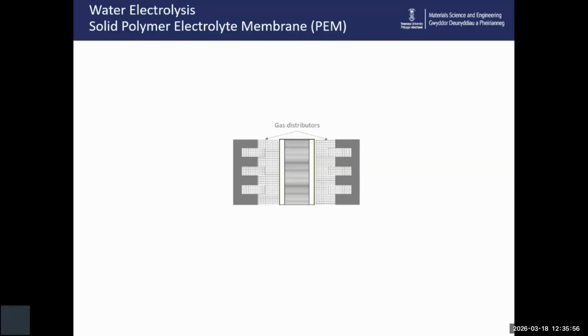The space between each end plate and the current collector is filled with a porous gas distributor, fabricated from sintered titanium. Deionized water is then fed through one end plate, via a series of channels, on the side of the cell that will become the anode. The current collectors are connected to a direct current DC power supply.